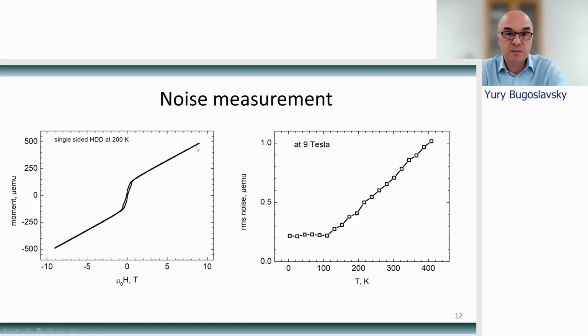To measure the noise, we simply zoom into the section of the curve at high field, calculate the statistical root mean square noise, and plot it as a function of temperature for a different set of curves, taken at different temperatures. What we get here is the plot on the right, which has a nice linear decrease of noise as the temperature decreases from 400 Kelvin to 100 Kelvin, and that's exactly what the Johnson noise should be behaving like. At 100 Kelvin, we hit the input limitation of our low noise preamplifier. But the overall result is that the machine is set up correctly, and it measures at the limit of what is possible for our set of detection coils.